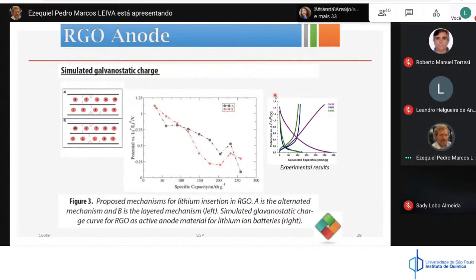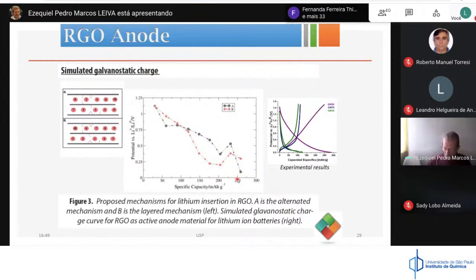And this is to show you the galvanostatic curve, where you see how the potential changes as a function of the specific capacity. You can see that, at least from a qualitative aspect, the curve of potential as a function of capacity is similar to this curve of the potential as a function of the specific capacity. That means that when you start to put more and more lithium inside the material, you get a potential which is very close to the lithium bulk deposition potential. But for a small number of ions introduced, the potential is about 1 volt over the reversible potential for lithium deposition.